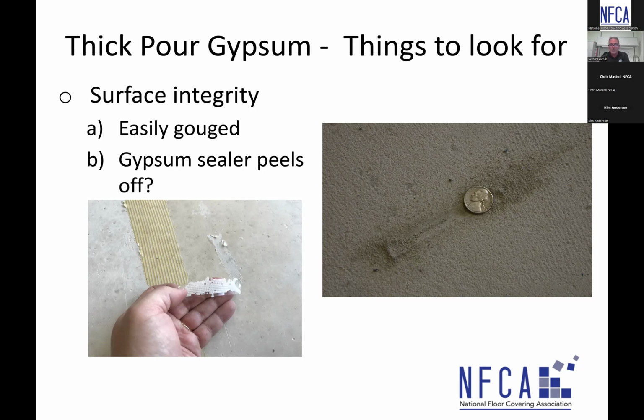For whatever reason, there's a very, very weak surface, and the primer that was used on the gypsum dried, and we're able to peel that film off, and then you have white on the underside. You shouldn't be able to do that with a primer on the surface of any material like that. That primer should soak in, dry, and you have a film.